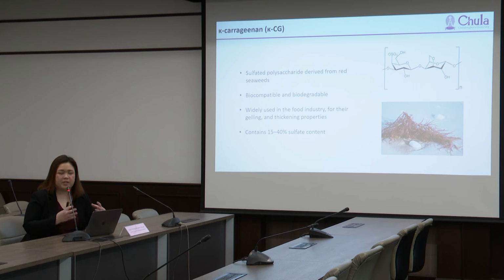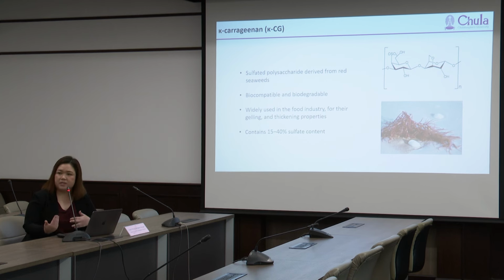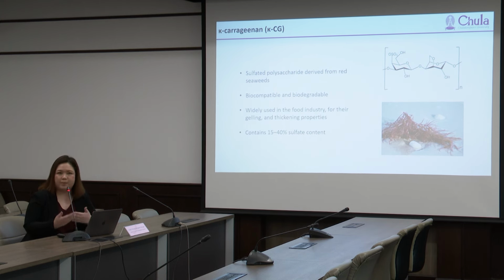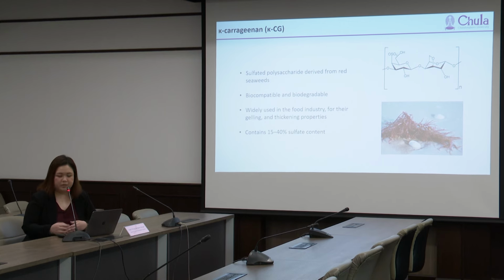However, when we use kappa carrageenan as a hydrogel, we always have a problem with the poor mechanical property, like Dr. Intouch presented earlier. So we cannot use that hydrogel as a wearable sensor because it has poor mechanical property. It's so fragile and really brittle. So we need to improve the mechanical property. We need to find a way to do that.